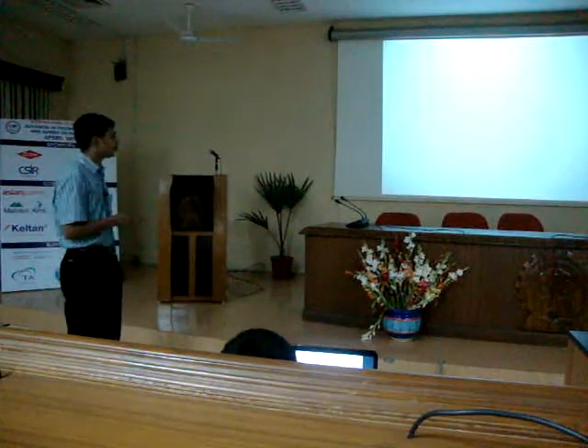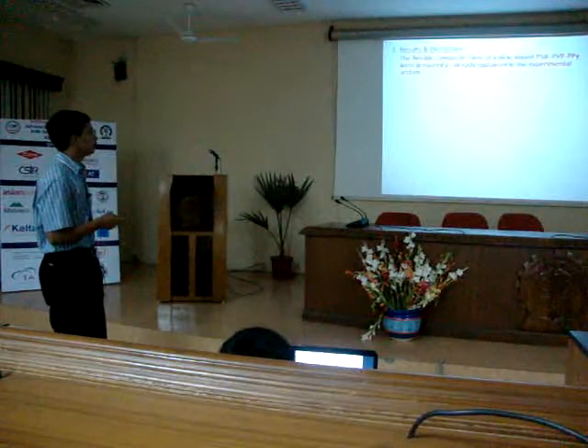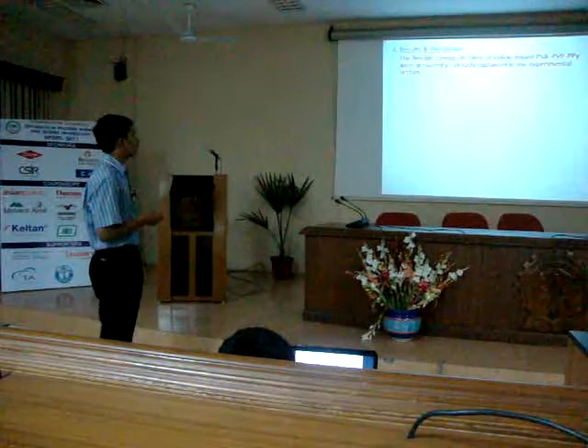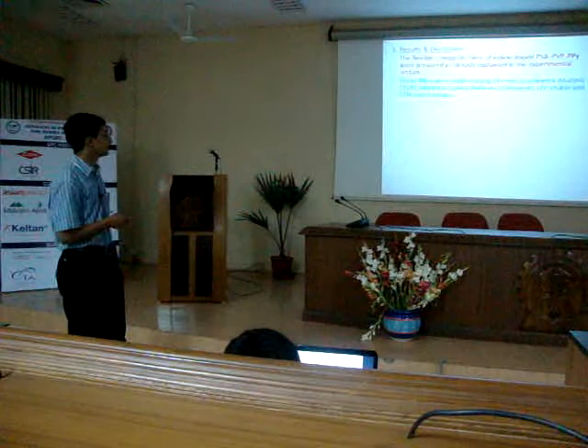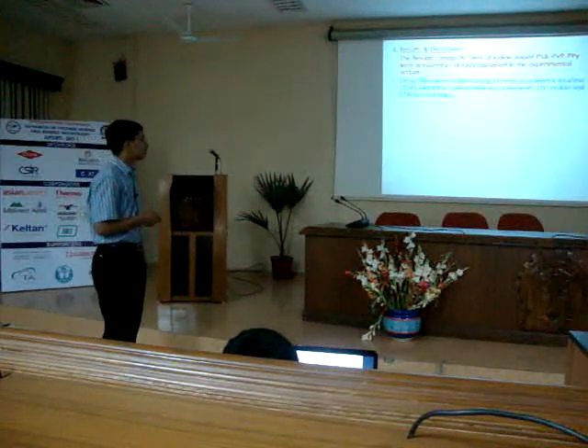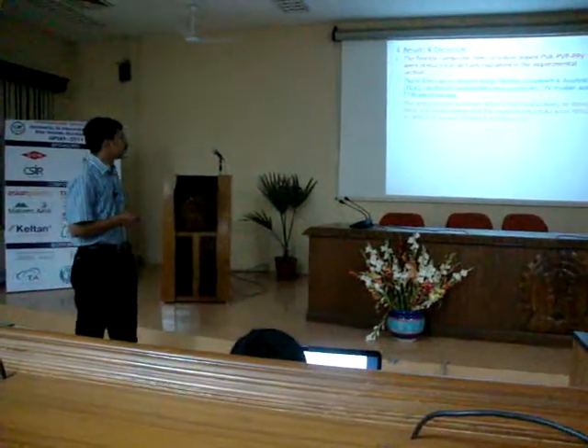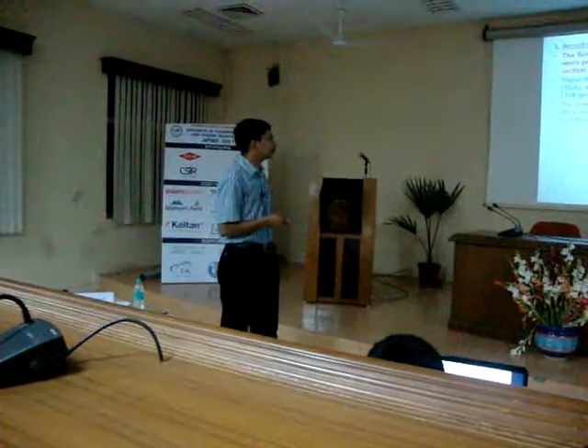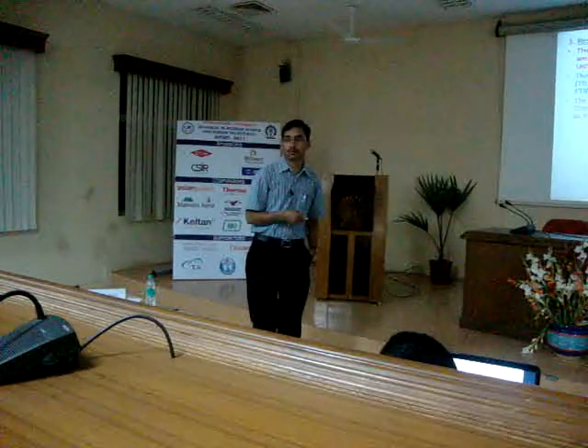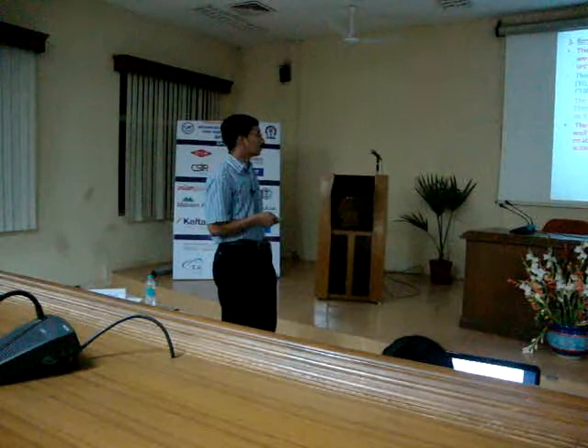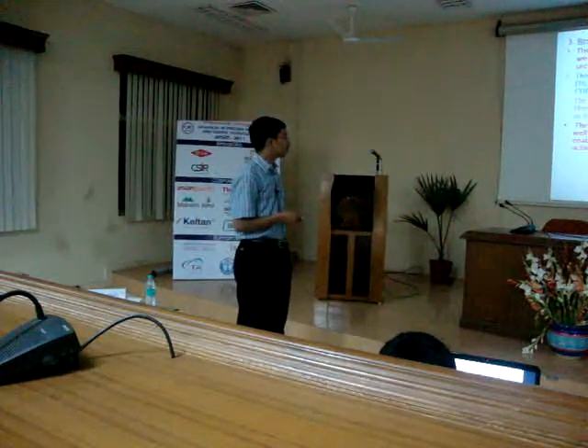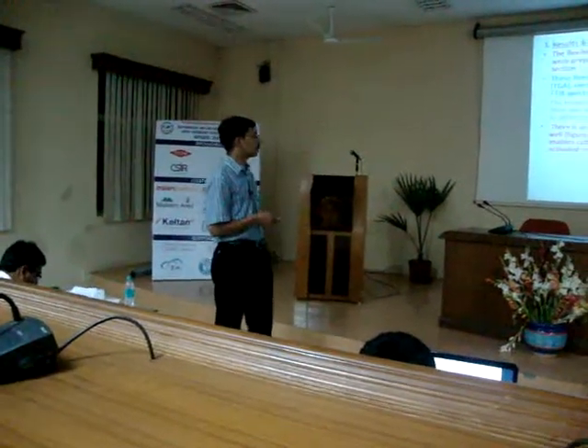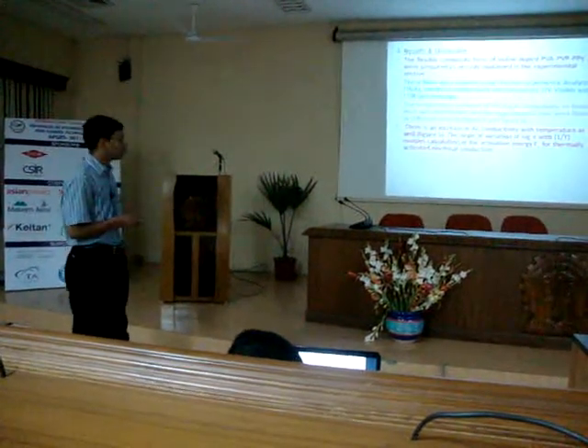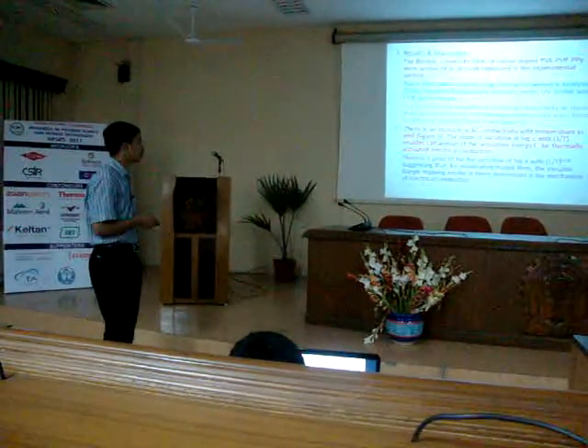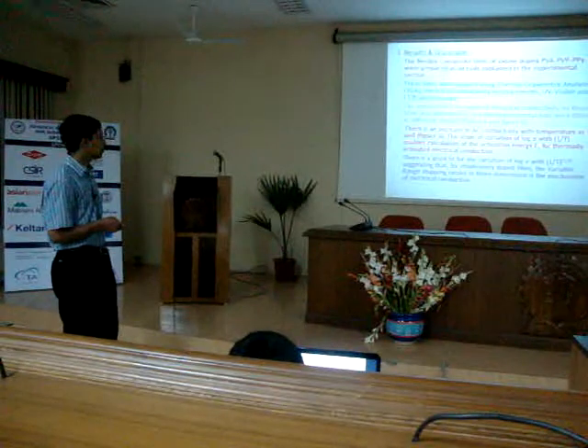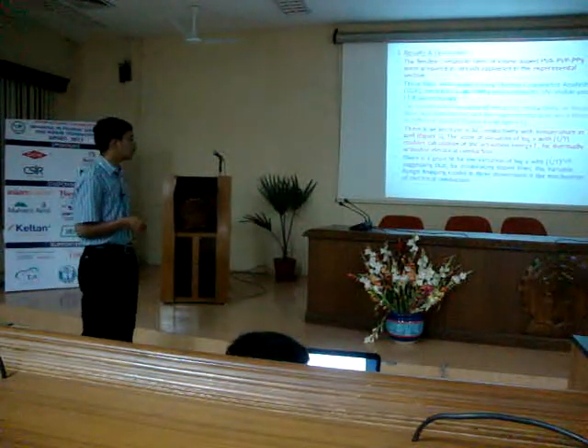So now comes the results and discussion. The flexible films of iodine doped PVA, PVP, PPY blend were prepared as already explained in the experimental part. These films were studied using thermogravimetric analysis, electrical conductivity measurements, UV visible and FTIR spectroscopy. The temperature variation of electrical conductivity on these films was determined and the experimental data were fitted to different models, as we saw in figures 4 and 6. Next, there is an increase of AC conductivity with temperature as well, in figure 5. The slope of variation of log sigma with 1 by T enables calculation of the activation energy EA for thermally activated electrical conduction. Next, there is a good fit for the variation of log sigma with 1 by T to the power of 1 by 4, suggesting that for moderately doped films, the variable range hopping model in 3 dimensions is the mechanism of electrical conduction.